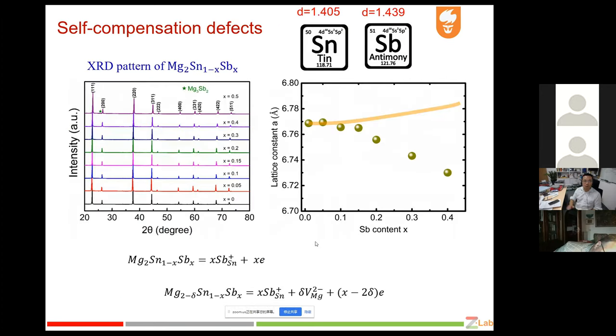Recently we did some new work. We added more antimony in this magnesium stannide, usually for carrier optimization. Usually people just add 1% antimony, but in our current experiment, we added almost 50% antimony in this magnesium stannide compound. It is very interesting. Usually the antimony is a little bit larger than the tin. However, in my experimental results, from the XRD pattern we calculated the lattice parameter, and we see that after we add more antimony, the lattice parameter decreased. This indicates that some new defects, magnesium vacancies, appeared.